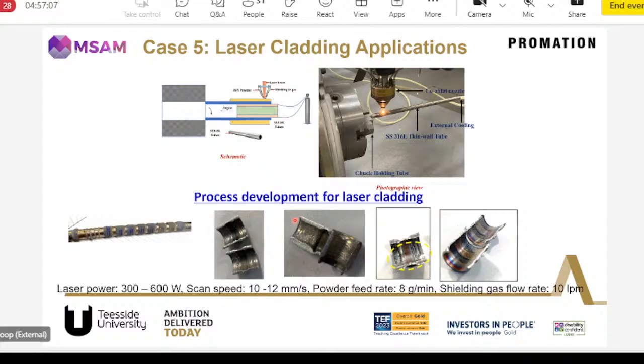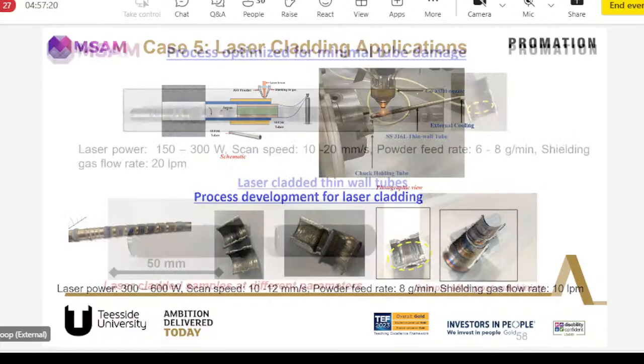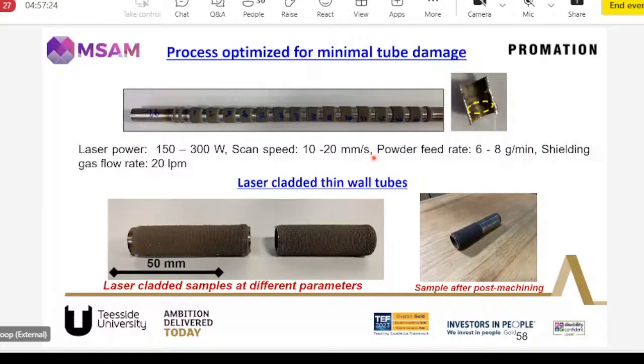Then we went into extra shielding. So we used argon gas for extra shielding. So we used a pipe and fit. We used argon gas as an extra shielding mechanism. Then what we could do is we could get rid of this damage within the interior of the tube, and we could get good bonding between the cladding and the tube, and the interior was also protected.